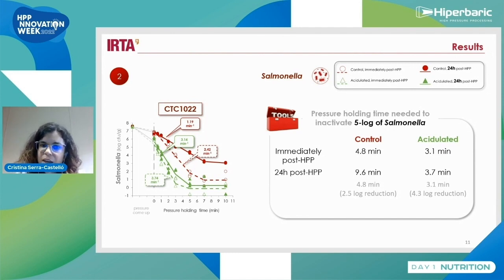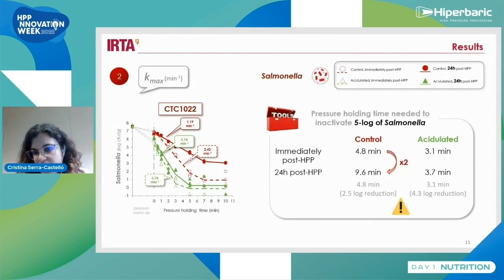If we focus on the results obtained immediately post high pressure processing, we can estimate that a minimum of 5 minutes will be needed to inactivate 5-log of Salmonella in control products. This time will be 3 minutes for acidulated products. However, if we look at the results obtained 24 hours post high pressure processing, this time will be doubled, rising to nearly 10 minutes for control products. In the case of acidulated products, this increment will be lower, but still higher than the one estimated immediately post high pressure processing. What this means is that if we validate our processes only considering the results obtained immediately post high pressure processing, we can overestimate the effect of high pressure processing.